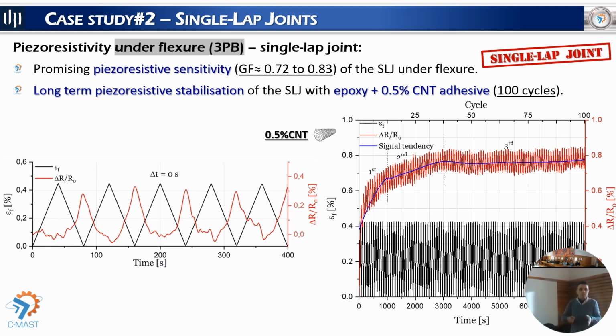This is not important for the sensor building because the most important characteristic of this system is the presence of a variation of the electrical resistance when the mechanical stress is applied. The way that it varies is defined by the movements of the electrical charge carriers inside the polymer matrix during the experiment. But this is not so important. What is really important is this variation, this amplitude of signal during the test.